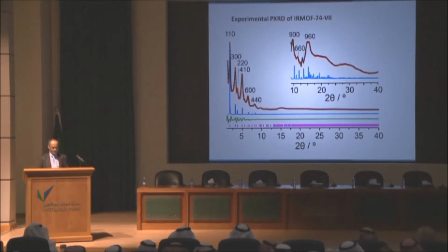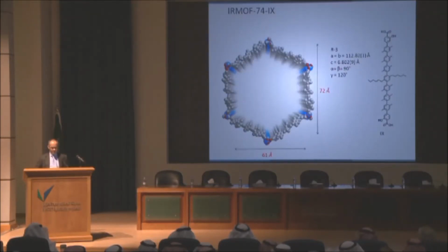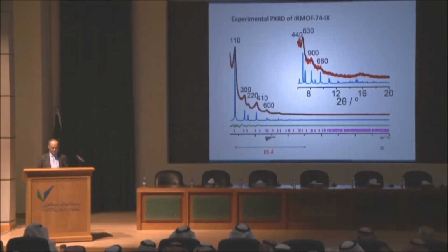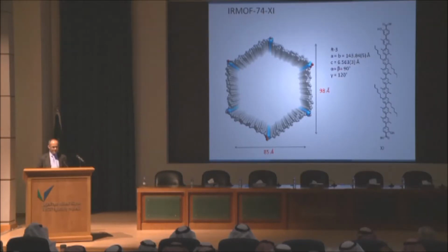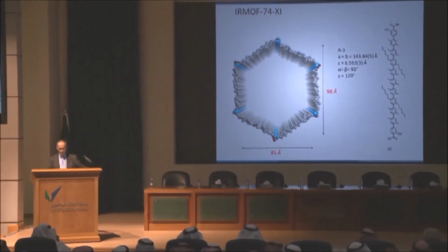I'm skipping over the characterization part. 9, 72 by 61. 11, 98 by 85 angstroms. This is the largest pore opening in a porous crystal ever made. And it's made by design. All these structures are based on the parent structure. All we're doing is stretching them out to open up the pores.